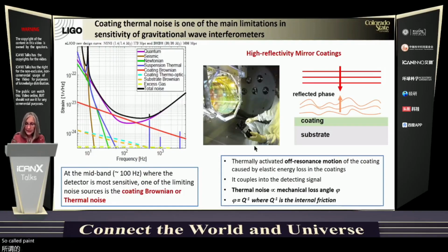Coating thermal noise arises from the thermally activated motion in the coating that leads to elastic energy loss. It couples into the detected signal and therefore adds noise to the detected signal. Thermal noise is proportional to the mechanical loss angle, and I will be referring to this measurement throughout my talk. This is a picture of the end-test mass of the LIGO interferometer. The substrate is fused silica, about 30 centimeters in diameter and about 30 centimeters long. What you see here is the reflection of the oxide coating.